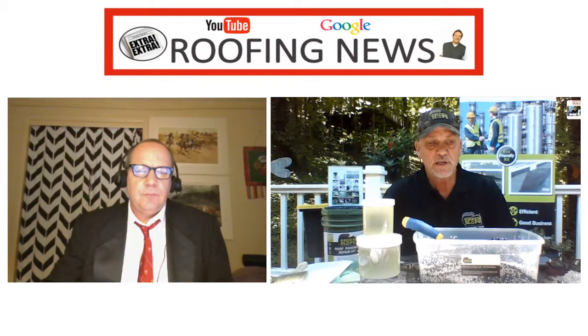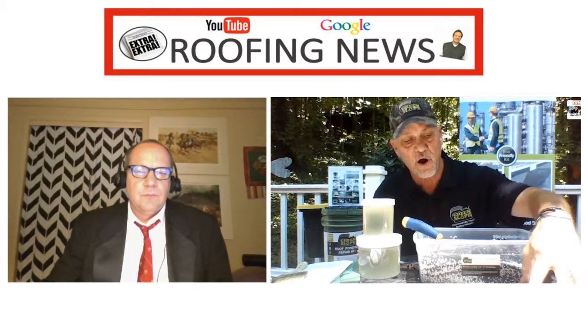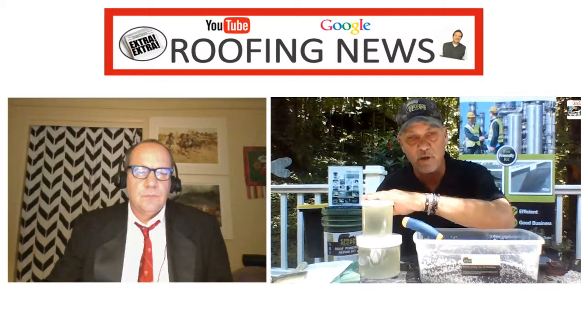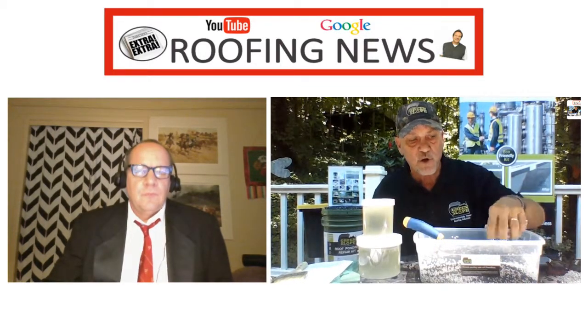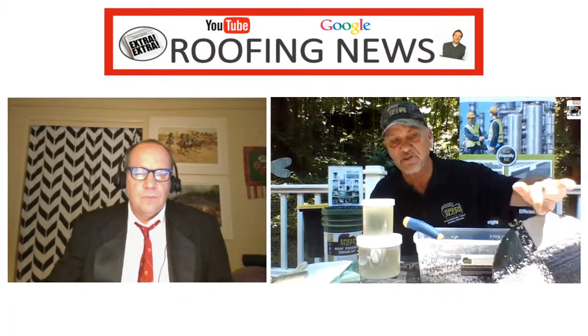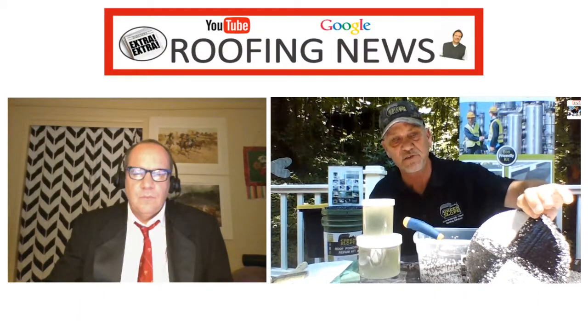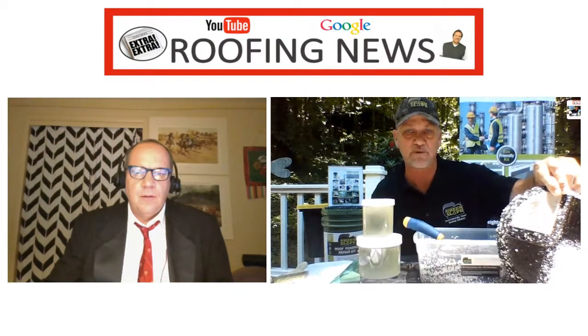What's interesting is I grew up old school. Rubber and asphalt products don't mix. It's a petroleum product. It breaks down the EPDM. Interesting with Green Slope is the adhesive formula we use encapsulates all the granules. So we have no problem putting typical roof cements, silver roof cements, emulsions and roof granules as a top coat. A lot of different options that you can do.